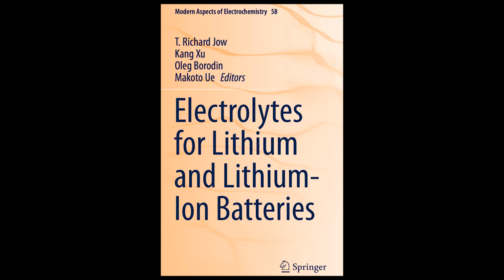Interestingly, ILs based on aliphatic quaternary ammonium, or AQA, cations show wider electrochemical stability windows compared to some other common ILs. Okay. Furthermore, it's been observed that lithium metal can be deposited and stripped, plated and removed, more cleanly in some AQA ILs without needing additional organic additives. That's potentially a significant advantage for developing lithium metal batteries, which promise higher energy density. Interesting. Enabling other battery types.